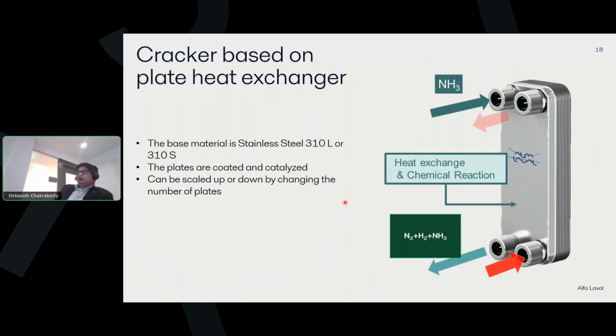We are using our heat exchanger and coating the plates and converting it to a cracker. So one channel is coated with cracking catalyst, and the next channel is for hot gas to provide the heat for cracking. And this is a very nice system because it is scalable up and down depending on the number of plates we could add, and also it has low pressure drop.